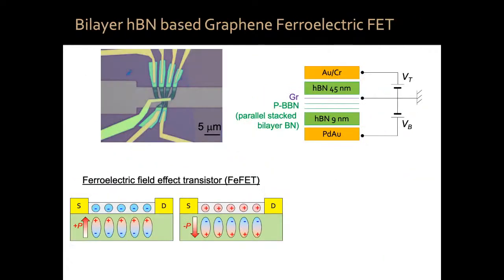So this is exactly what we did. We created these parallel bilayer boron nitride layers. And in order to investigate its ferroelectricity, we deposited a graphene sheet on top. And then we deposit more dielectric and a bottom and top gate so that we could apply an electric field. What we did is we created a ferroelectric field effect transistor. A transistor where the conductance, the resistivity of the transistor, depends on the polarization state of the ferroelectric.